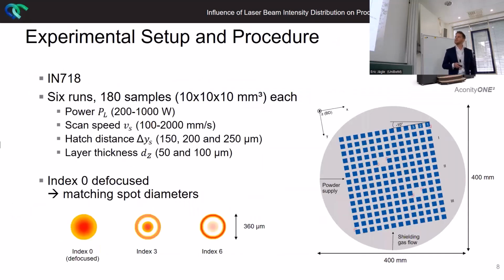To investigate this laser, we ran a time-consuming and broad parameter study with index 0, the Gaussian one, index 6, the ring beam, and index 3, the hybrid one, with hundreds of cubes for the nickel-based superalloy 718. One important thing for us was that we kept the processing conditions absolutely constant: the inclination angle of the laser, that means the position on the substrate plate, as well as the shielding gas flow, etc. In this context, we defocused our spot diameter from index 0, the Gaussian one, to the outer diameter of index 3 and index 6.